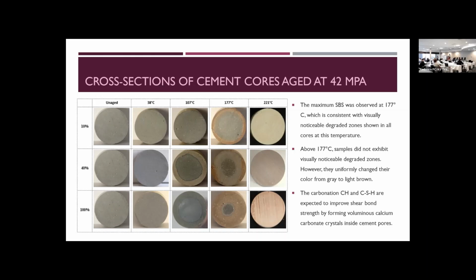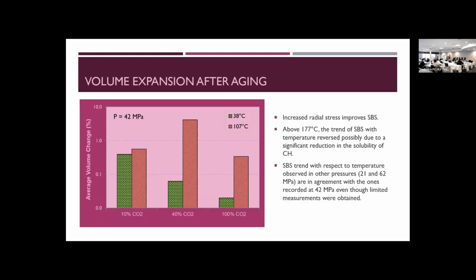That was one of the things that we're going to show you later when we've done some other types of investigations. We measured also the volume expansion after aging, just to look at the average volume change. You can see here that this is for 42 megapascal. We have noticed some changes here. Increasing the radial stress will improve the shear bonding. That's a very interesting element because, as I remember, we discussed yesterday the cement shrinkage as well as the thermal expansion of the cement. Actually, all the trends that we observe on the shear bonding strength with respect to temperature are in agreement with other ones that were recorded at 42, 21, and 62 megapascal.